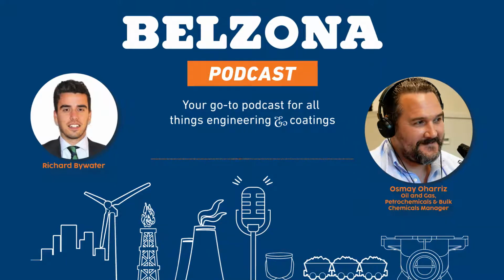And this is how you combine relatively inexpensive material with costly materials. But this introduces another problem, because as you're using different materials with different characteristics, then you might actually end up with bimetallic corrosion if you do not design this, let's say, ensemble of different materials correctly. So that's a different subject. Now, cathodic protection, on the other hand, reduces corrosion because what it does is it makes a surface less prone to oxidation. It could be pretty complex. It could be also expensive.